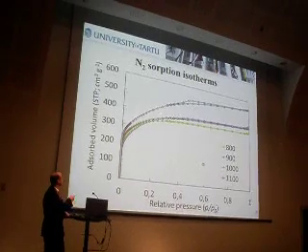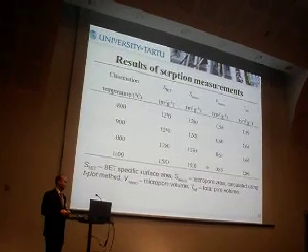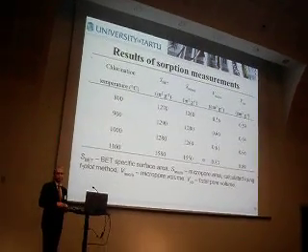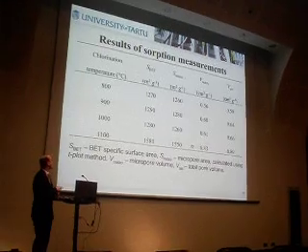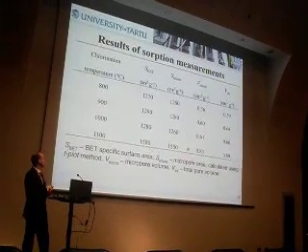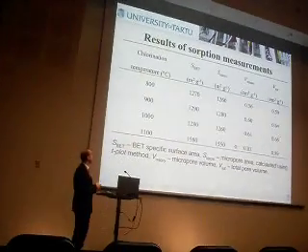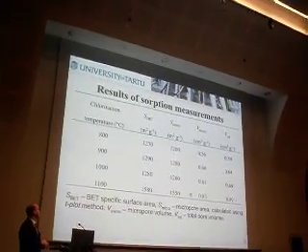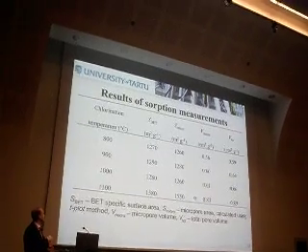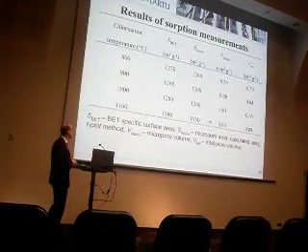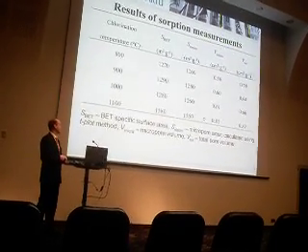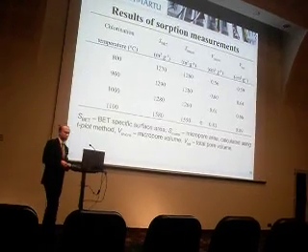So the material we synthesized at 1100 degrees. And also here are the results from sorption measurements, all in a graph. And what I'd like to stress is the highest specific surface area for the material that was synthesized at 1100 degrees, and there is about 1580 square meters per gram.